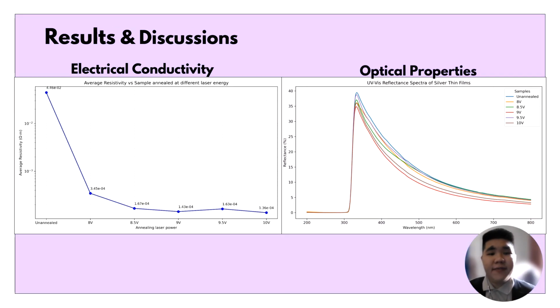Coming to our results and discussion, our results were significant. As shown in the electrical graph, the unannealed silver starts with a high resistivity of 4.76 times 10 to the power of -2 ohm meter. However, after laser annealing at 10 volts, this dropped drastically to 1.36 times 10 to the power of -4 ohm meter. This two order of magnitude drop confirms that the laser successfully recrystallized the silver.